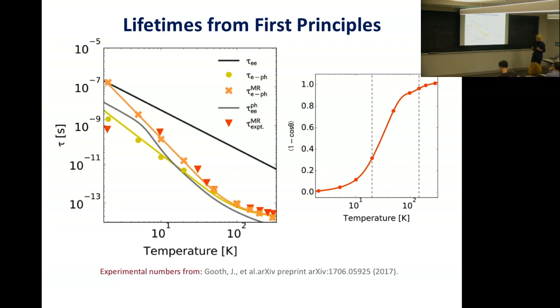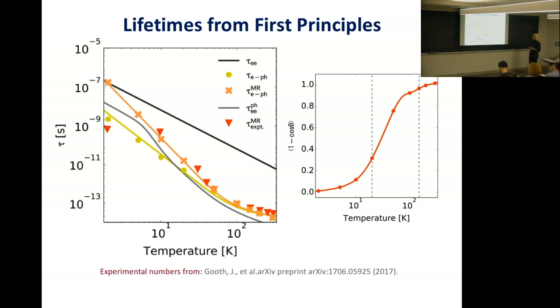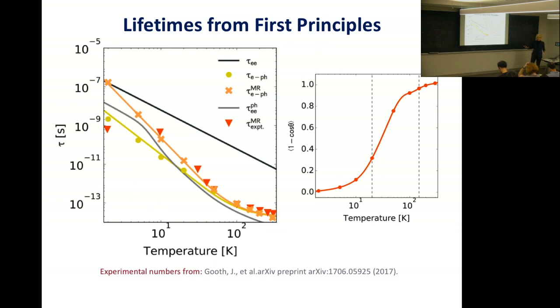We characterized the small-angle scattering and compared quantitatively with experiment from collaborators working with Claudia Felser. We see excellent agreement. The inverted red points are experiment — they don't have data at every temperature, because dense sampling in experiment requires thousands of hours. These transport lifetimes are computed using ab initio scattering matrices and put into a Boltzmann transport equation. They are transport lifetimes, not single-particle lifetimes. We then put them into a spatially resolved Boltzmann solver in order to see the hydrodynamic Poiseuille flow appear.